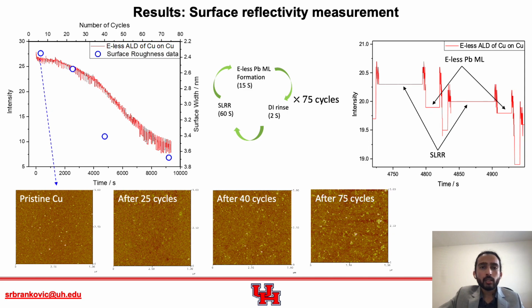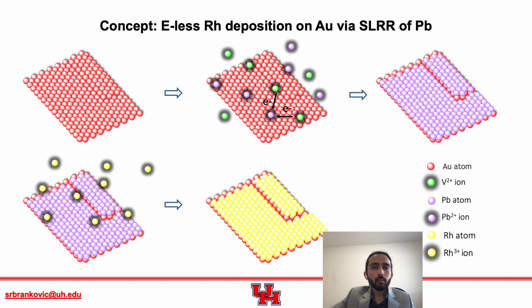So overall, in general, this setup helps us to monitor the electroless deposition process in situ when we cannot have any electrical connections or the cases where we are not able to measure open circuit potential. Now as a second part of the evaluation process for this setup, we demonstrate heteroepitaxial deposition and sensitivity of the setup for the same as well. So we deposit rhodium on gold via SLRR of lead monolayer.